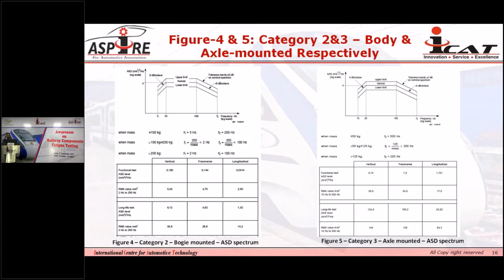If the mass of the test component is more than 50 kg and less than or equal to 125 kg, the lower frequency will be 10 hertz and the higher frequency we have to calculate as 125 divided by the mass of the component, into 200. So it will give us the higher frequency. If the mass of the test component is more than 125 kg, there is a fixed higher frequency, that is 200 hertz. This means the lower frequency is fixed in this case, and the higher frequency we have to calculate from this formula.